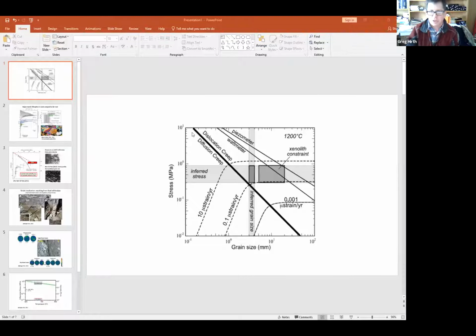The other thing it's showing is a boundary based on the lab data between the dislocation creep field of deformation and the diffusion creep field. So what you can see is increasing stress favors dislocation creep, increasing grain size favors dislocation creep. And the things that we pointed out were, while the diffusion creep model could work, the grain size that you would need for it to work actually plotted where you would predict dislocation creep would be the dominant mechanism. So there was some inconsistency there.